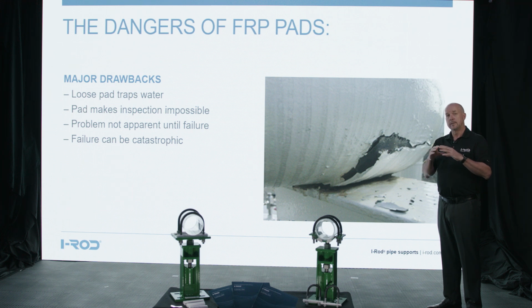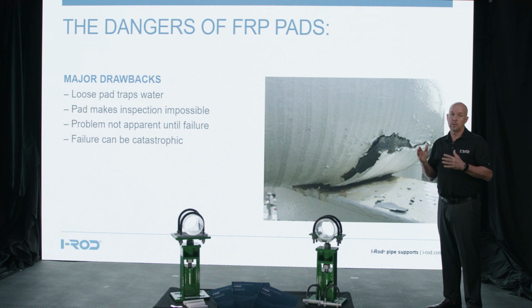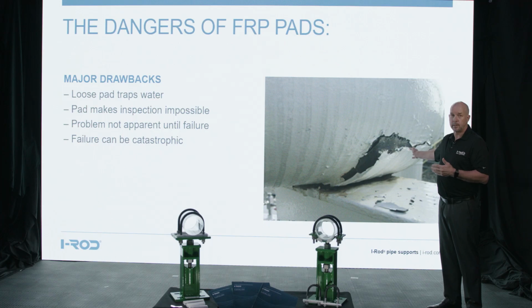The problem is that steel and fiberglass have a different coefficient of thermal expansion. So the steel is expanding and contracting from thermal change at one rate, fiberglass at a different rate. Something has to keep up with one moving a lot and the other one moving less. And in the beginning, the adhesive can keep up with that, but eventually it separates and allows a little crevice. You just need a small pinhole for moisture to get in. Moisture gets in, starts to have corrosion happening, and that's what you see here in this image on the right. The pad is completely separated, moisture's gotten in, and there's lots of corrosion happening.